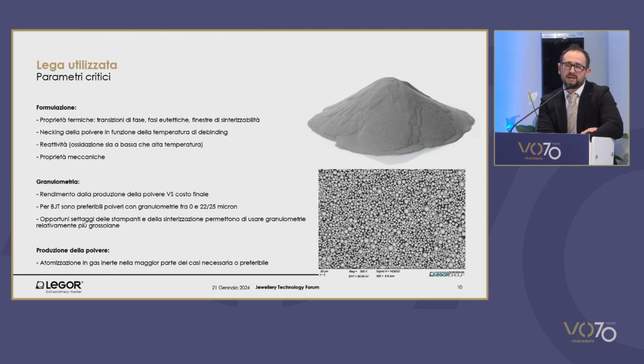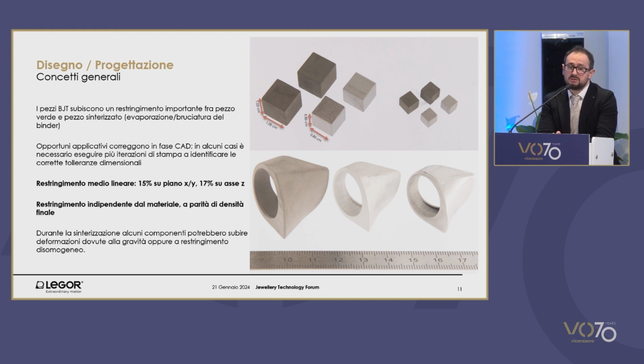There is a trade-off between the yield of the powder. We have perfectly controlled atomization phases, but I have to take into consideration a phase which would cost a lot if you're using precious material, and the optimum grain size, which according to the literature is very, very low in binder processes. So you need to select whenever possible an alloy that gives you a good production yield in terms of the powder, and the need, especially for jewelry and fashion, requiring a density equal or close to 1.